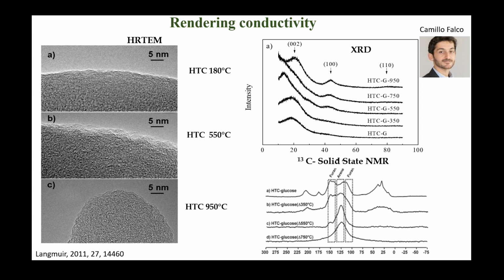But the nice thing is that you can take these carbons that you make at low temperature, nanostructure them the way you want and carbonize them further. And you don't change the morphology. However, of course, you will change their microstructure. So you would go from something that is completely amorphous to something that is a hard carbon type material, something that is non-graphitizable, but you can have a lot of graphitic domains in it. So you could see the 002, the 100 peak.